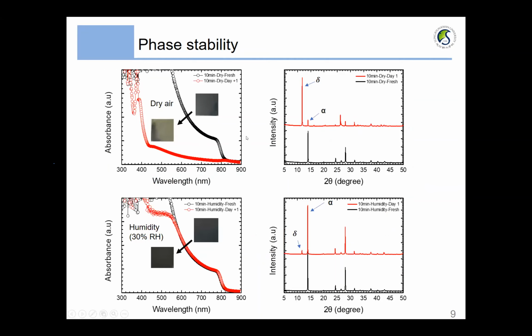First of all, we observed that there is a significant improvement of the phase stability in the films annealed under humidity. The left-hand side is the UV spectrum, and the right side is XRD. You can see that a significant amount of the alpha phase is sustained in the films annealed under humidity while maintaining light absorption ability, while the dry air shows a complete loss of light absorption with a significant amount of the delta phase observed.